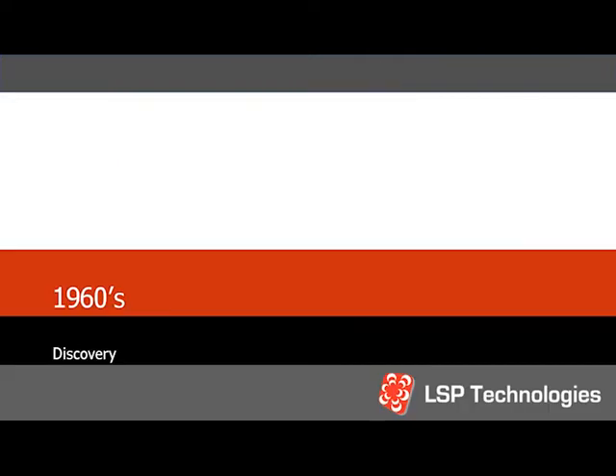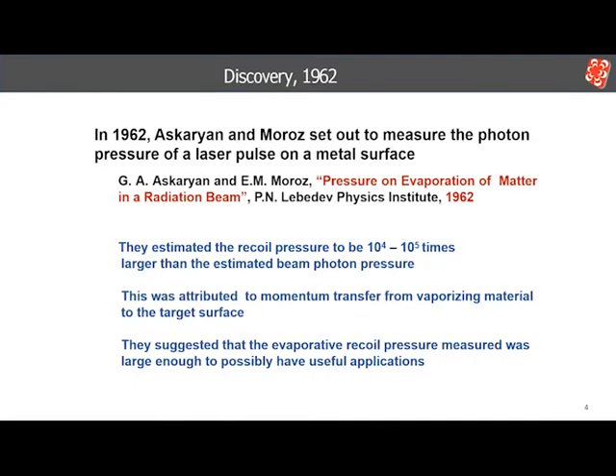We begin in the early 1960s. The triggering event occurred in the early 1960s when two Russian scientists, Askaryan and Moroz, set out to measure the photon pressure of a pulsed laser beam on a target. What they measured was a pressure 10 to the 4th to 10 to the 5th higher than the estimated photon pressure. They suggested that what they actually measured was probably the recoil pressure from the material vaporized from the target surface by the laser beam. They also suggested that this might have useful applications.